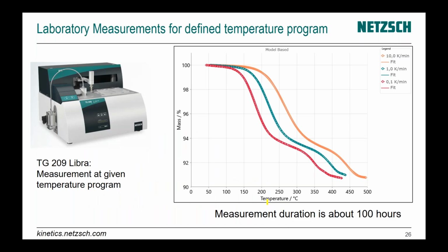How it works? We go to laboratory, make measurements, have 2 steps, make the modeling. You see that points are our experimental data from 0.1 K per minute to 1 K to 10 K per minute, and lines are fit, and they have a good agreement. All measurements are about 100 hours, and now we would like to make predictions for several years.